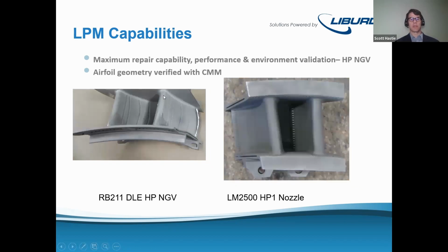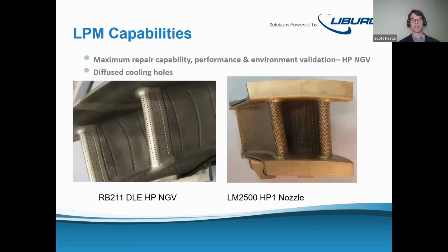After consolidation in the heat treatment, here are some pictures, and now you can see that leading edge that was once full of cooling holes no longer has any cooling holes, and it's pretty neat to see. On that LM2500 part, all of the showerhead cooling holes on the leading edge, as well as all of the cooling holes along the concave surface of the part, are filled up with the powder metallurgy. And this is the exciting thing. Afterwards, we have a lot of machining to do. We use either sink EDM or fast hole drilling, or sometimes EDM milling to create these diffused cooling holes on this component, and then the rest of them are just straight through cooling holes.